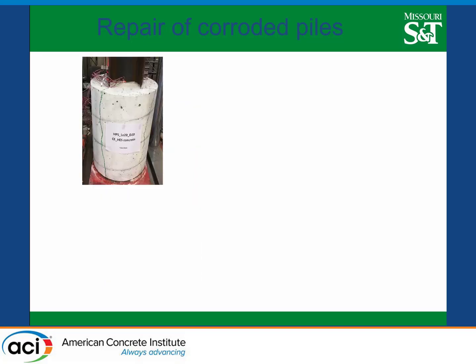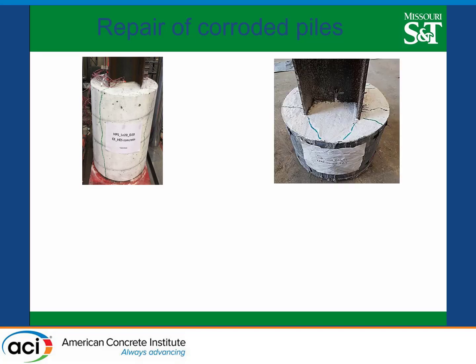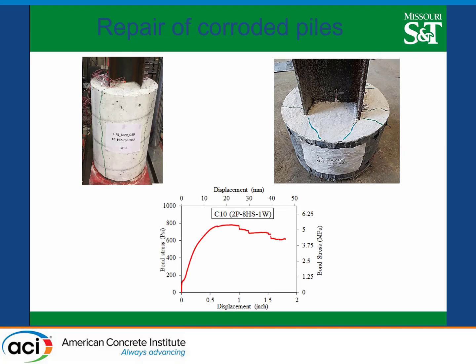So this is just to give you an idea about the testing. This is the conventional cracking, what you would expect, with different strengths of concrete as well, and different lengths. This is another one over here where we used the carbon fiber and the grout. One of the questions was whether to use steel studs or not, and this was also something that we investigated.